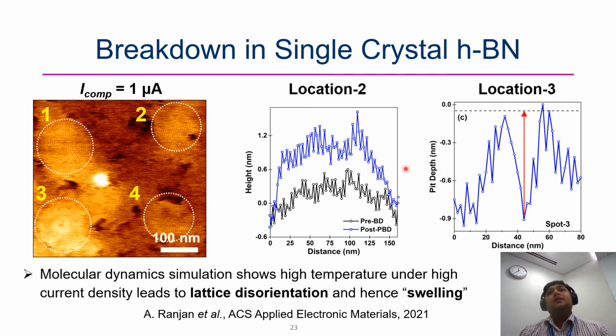So we did some molecular dynamics simulations with our collaborators, and what we have found is that when we do this kind of breakdown experiment, with the current around 1 microamp or higher, the temperature reached at these localized sites is very high, and this can lead to lattice disorientation. Therefore this is the reason we are seeing amorphization at these localized sites, and this may lead to swelling as well.